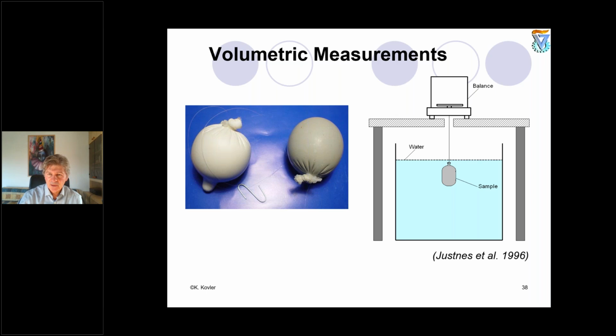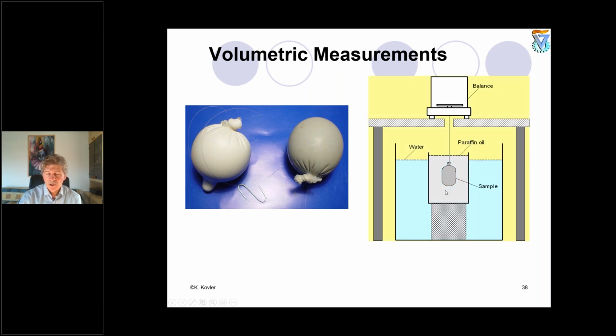So this specimen located in the membrane, which is a condom, is immersed in water. By the way, instead of water, we recommend using a more viscous liquid like oil or paraffin oil, which is less penetrating.